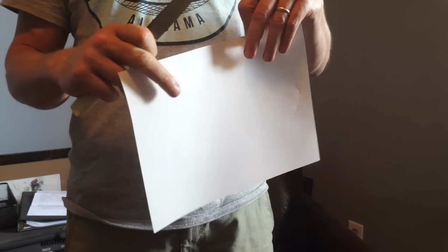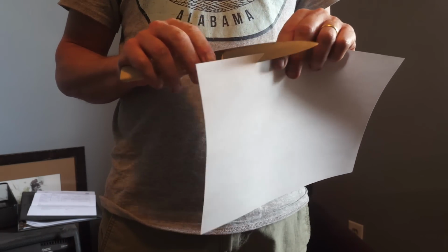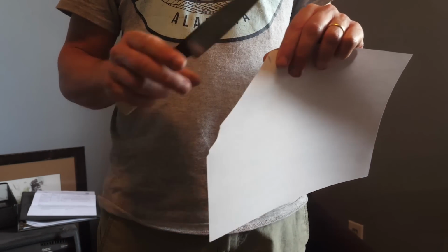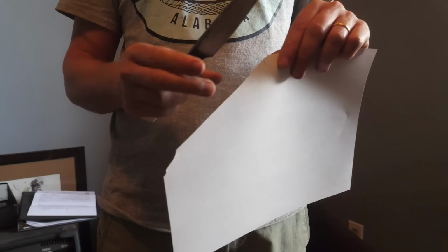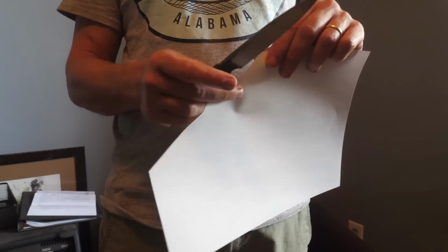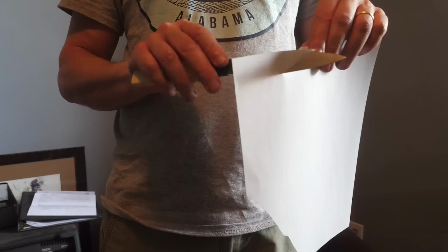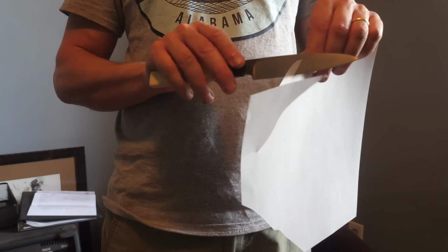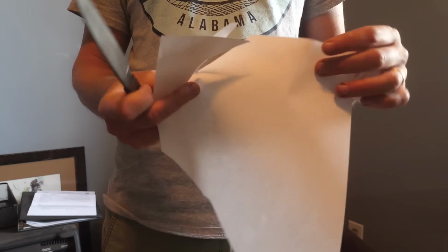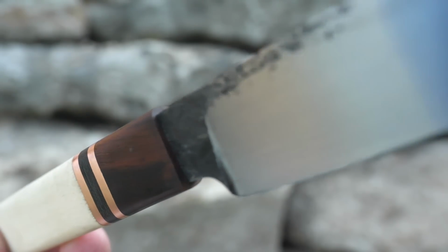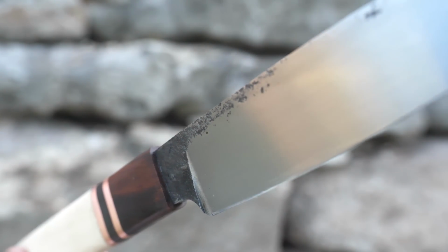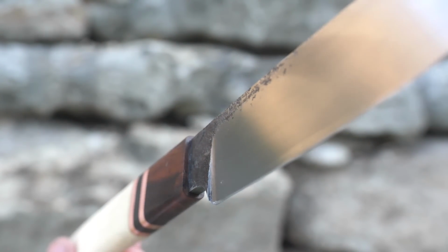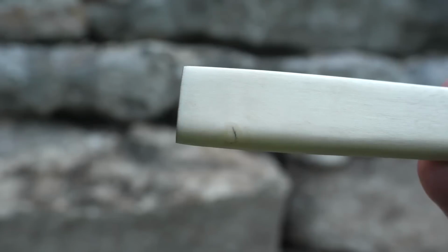So the cut test. To say this has a toothy edge is being generous, and I suspect the grain size here is still too large. Our first normalization cycle at 1550 is great. It's above the A3 line for something like 1050, but it's too low for something like 1040. And it makes me wonder if this steel is closer to 1040 than 1050, or 0.4% carbon, which is very low and a strange choice for a kitchen knife. It makes me wonder if these are cheap production knives.